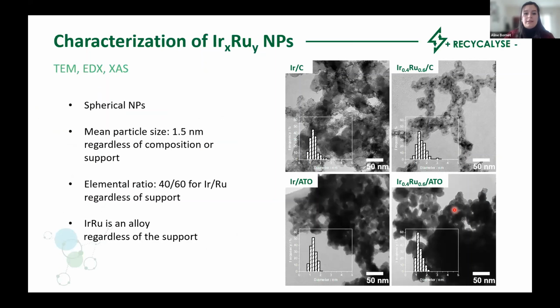We then perform some characterization of the nanoparticles, first by means of TEM, and we could see that the nanoparticles are spherical and that they are better dispersed on the ATO support than on the carbon, where they form small aggregates like here. Then the mean particle size was also determined, and it is about 1.5 nanometer for the IrRu composition. EDX was also performed to determine the elemental ratio between iridium and ruthenium, and it is about 40 to 60, regardless of the support. And finally, XAS, or X-ray absorption spectroscopy, measurements were performed to identify the nature of the iridium-ruthenium catalyst, and it was found that the nanoparticles are an alloy, and so they are not segregated particles.